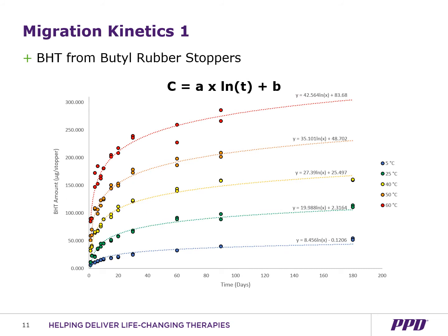In this first plot shown here, we have the extracted BHT amount on the y-axis versus the duration of the study on the x-axis, and each curve corresponds to a different extraction temperature. As expected, the extracted amount of BHT increased with time as well as increased with extraction temperature. So the higher the temperature, the more BHT that was generally extracted.